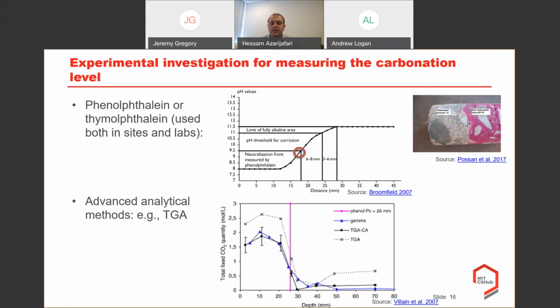The calcium, when in the ranges of the temperature that the calcium carbonate is dissociated and completely burned, we can have a good estimation of the mass loss that is attributed to the calcite or the calcium carbonate over there, and we can compare it with a controlled mixture which is not carbonated to understand the amount of calcium carbonate and consequently the amount of CO2 absorbed by the concrete mixtures.